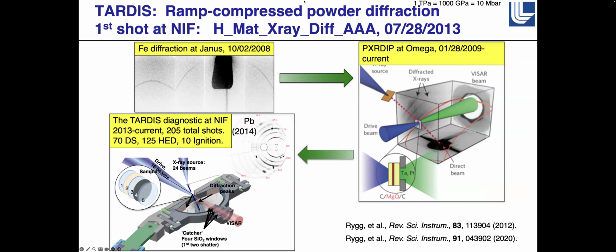So we first used this technique in 2008 at Janus at Livermore. It was a lot of fun. It turned out on our third shot, we actually got this data. This black region is what we saw in the first two shots, because we used a very simple image plate holder, and we found that we were getting a lot of X-rays through a centimeter of aluminum, which surprised us because the helium alpha radiation from iron is at about 8.3 kilovolts, which should get absorbed by a factor of 1,000,000 or so through a centimeter of aluminum. But we were getting very dark signal.